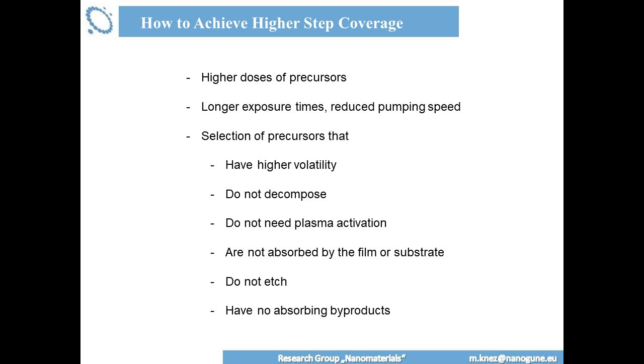They should not etch the surface. I did not talk about that. There are some precursors which etch away the surface. We heard this yesterday also in some talks that, for example, what was it? TMA can etch zinc oxide surfaces. So just by converting the zinc oxide into dimethyl zinc, which evaporates again, so you etch the surfaces. And here you have also the problem that during the deposition, if you have some substrate or previous deposition, you may etch it, so you should not. You should look into that.